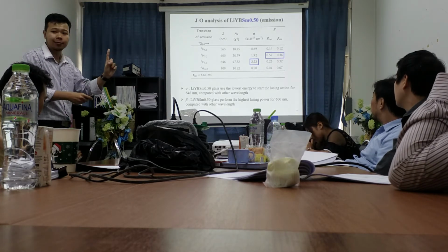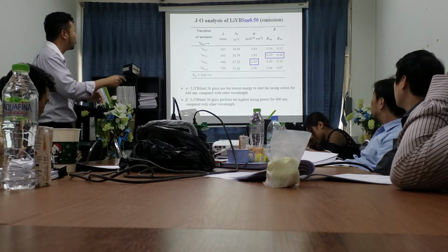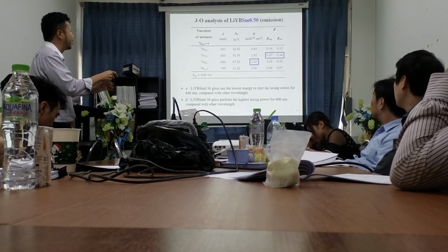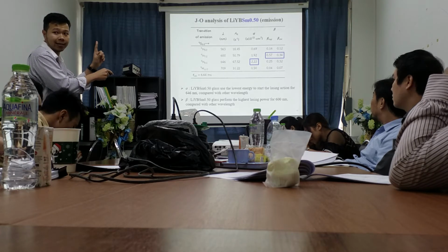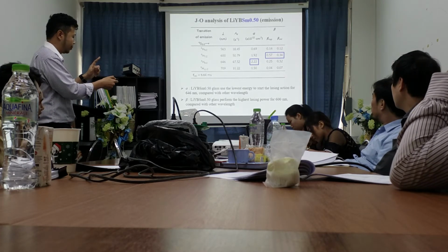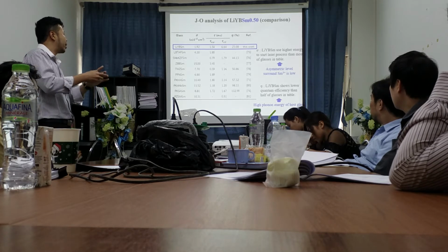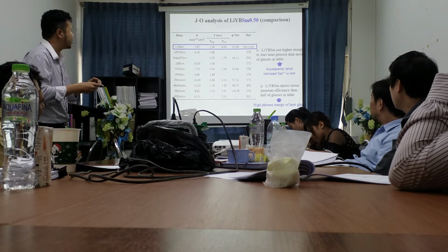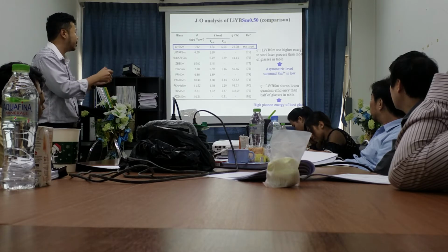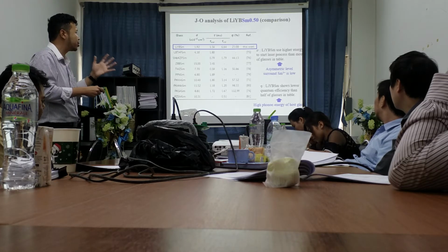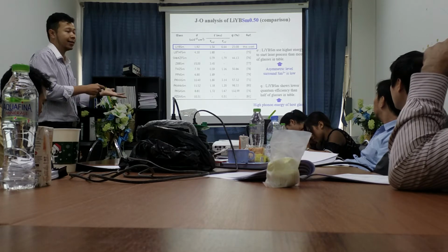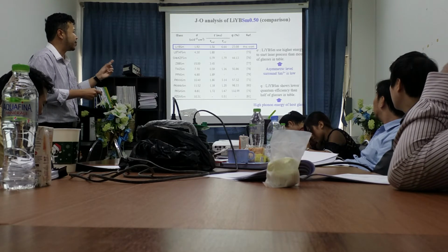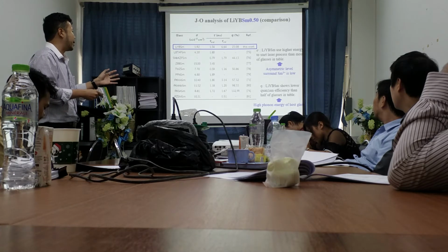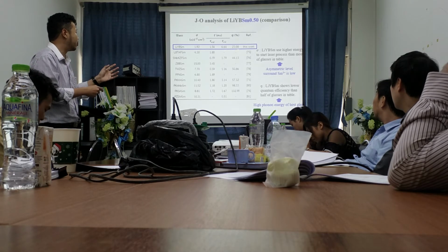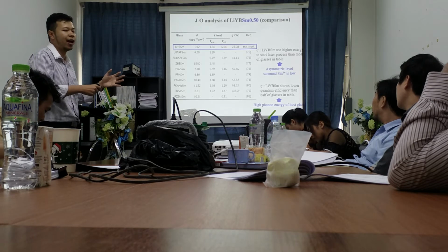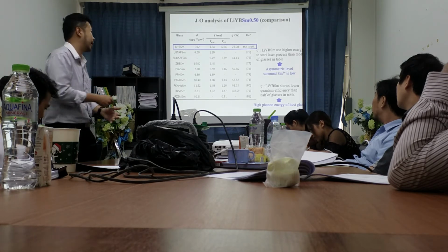However, I need to choose one to compare with the other glass, so I chose this 600 because in the emission peak, it shows the strongest emission peak for the 600. And of course, when compared with the other glass, my glass is not good. Even the energy used to start the lasing action needs high values because the asymmetry level is low, and the quantum efficiency is also low compared with the other glass because of high phonon energy and low vibration in our glass.